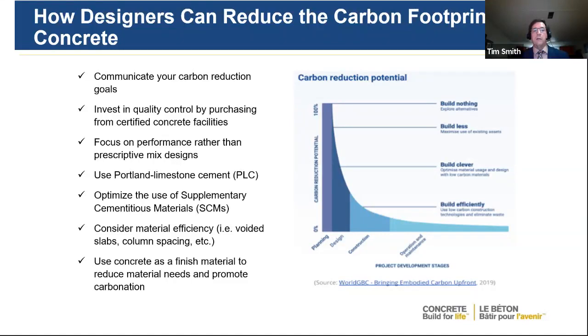They can use the Portland limestone cement, they can use supplementary cementing materials, and you also want to consider the efficiency of designs. If you only need a 32 MPa concrete for a sidewalk or curb and gutter, because that's what CSA A23.1 says, you don't have to provide a 35 MPa, because if you provide a 35 MPa, you're actually increasing the CO2 footprint of that concrete, and you don't really need that strength. So follow the CSA standards on what's required, and that'll help you optimize your mix design and minimize that CO2 footprint. You'll also reduce your CO2 footprint by allowing the use of these supplementary cementing materials and the Portland limestone cement.